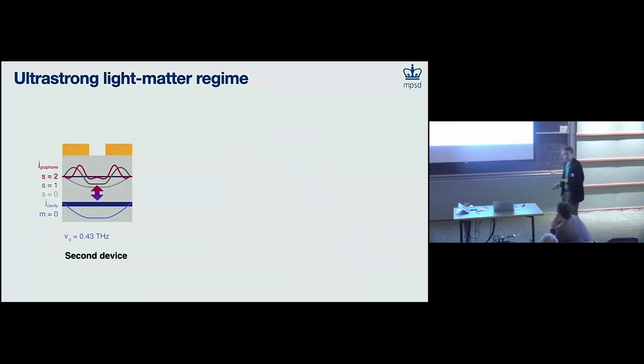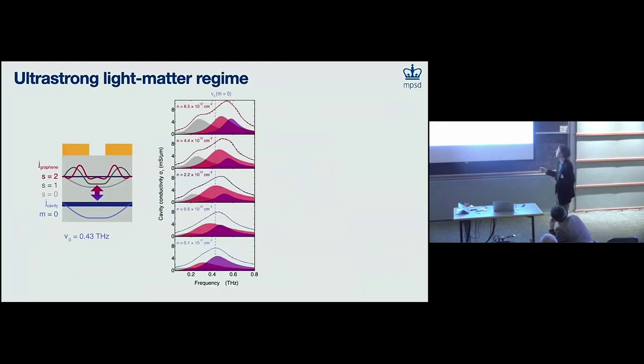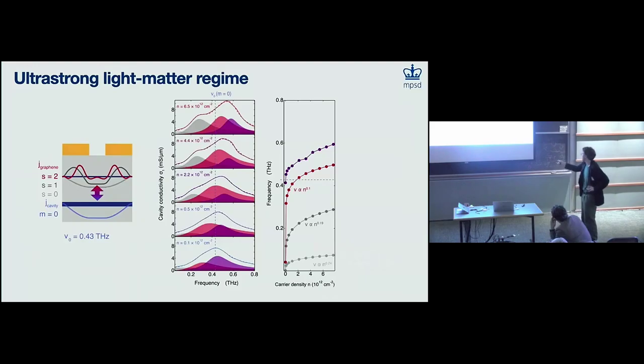So we built a second device. In this device, we now intentionally centered this cavity mode right in the middle of our bandwidth, so it would be directly on top of the 3 graphene modes. That means the spectrum that we measure, we expect to be inherently more congested, which it is. Here I'm showing a handful of carrier densities. But if we fit this very carefully and transparently, what we find is that we can fit the data well. And if we fit each of these Lorentzians versus the carrier density, we get things like we've seen before.